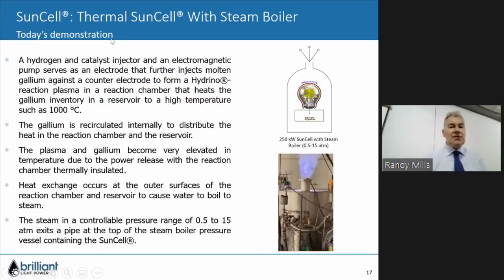So today's demonstration was the thermal SunCell with a steam boiler. How it works is, as I said before, it has a molten metal injector that injects molten gallium against the counter electrode. We run a high current through that. We get tremendous power from the Hydrino reaction. It heats up the gallium inventory, which is recirculated internally, to about 1,000 degrees centigrade. And then that heat is transferred through the wall to the water and causes the water to boil. And then we can control the pressure in the reactor by controlling the size of the outlet or the aperture of the boiler. So we can achieve and controllably produce steam in the half atmosphere to 15 atmosphere range.